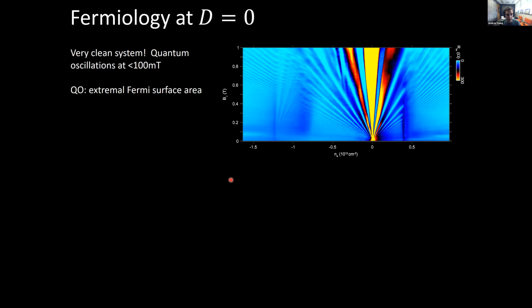So you can actually try to map this out very precisely using quantum oscillations. These systems are very clean. Their mean free paths are many microns. So even at very low magnetic fields, you can resolve oscillations in the resistivity plotted here, which probe the extremal area of a Fermi surface. And then we can Fourier transform these, and this is what a measurement looks like. You can see even from 100 millitesla, you start to see many oscillations in the resistivity, which develop and have various complicated features. You can plot this as a function of 1 over B and then Fourier transform that. And then for the plots that I'll be showing you, we're going to take those Fourier transformed frequencies and divide them by the total density.